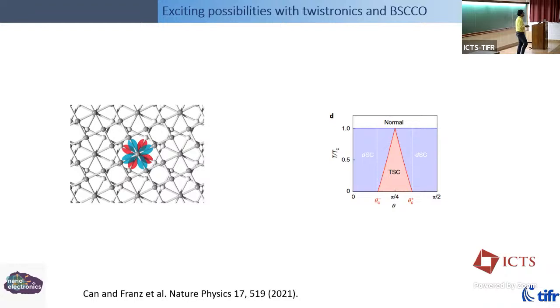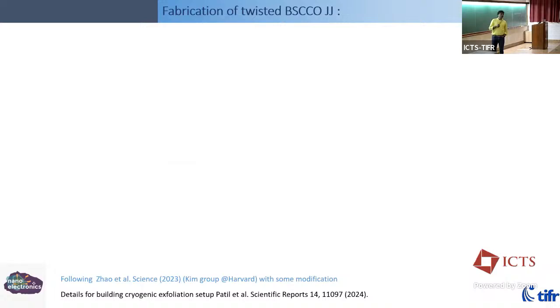Okay, so this was certainly very attractive, that you can have topological superconductivity at temperatures like 50 Kelvin, which is unheard of. So a lot of people got interested in it. But one of the challenges in this material is that it's extremely difficult to work with. You exfoliate it and you leave it for a couple of hours, it's actually degraded because the oxygen in BISCO is metastable. So you get off-stoichiometric stuff very quickly. And that's why there are not many people.